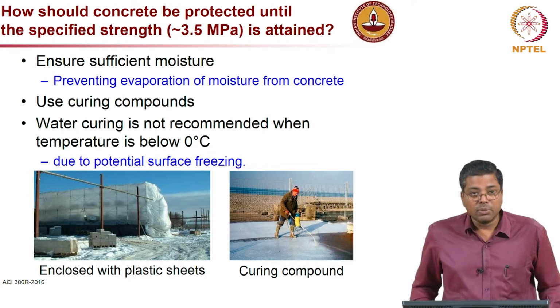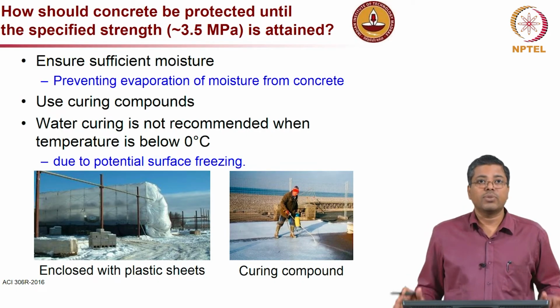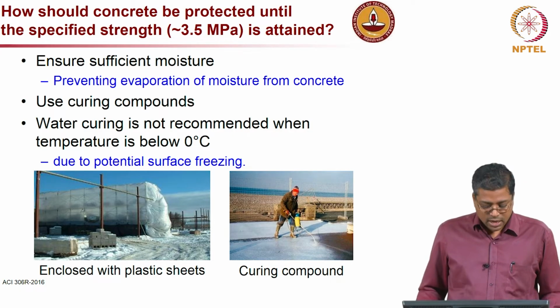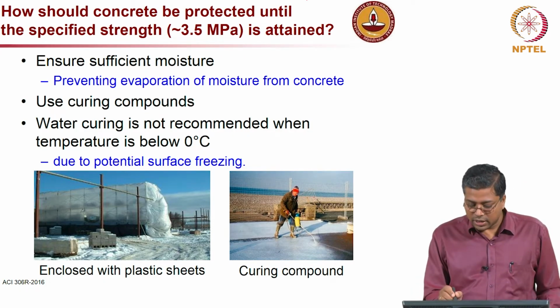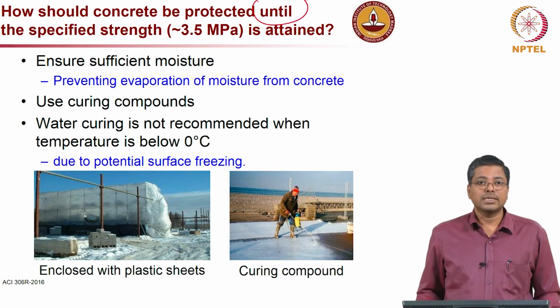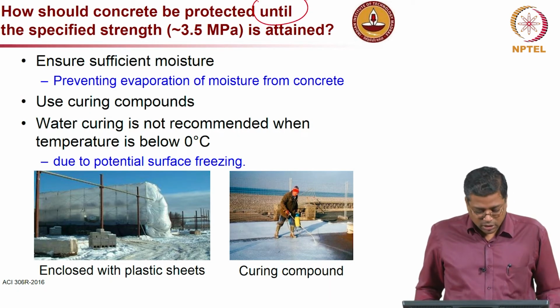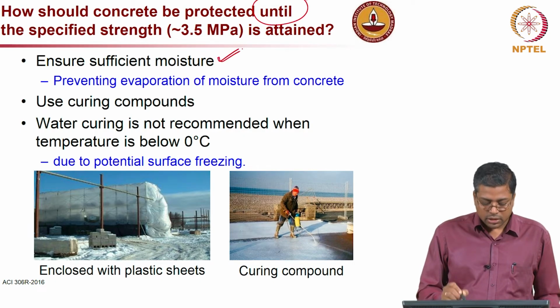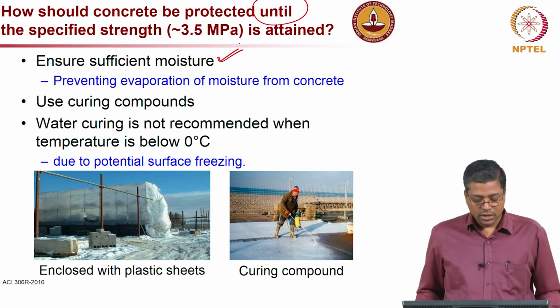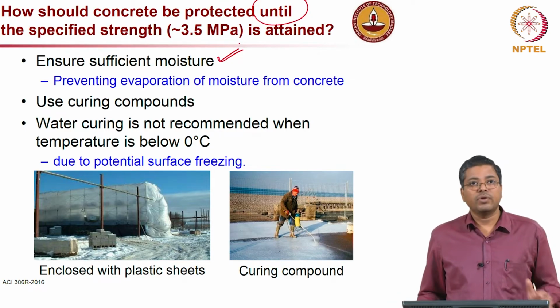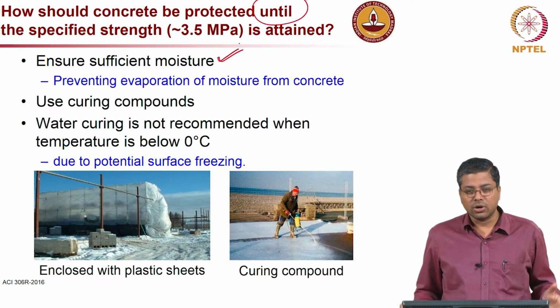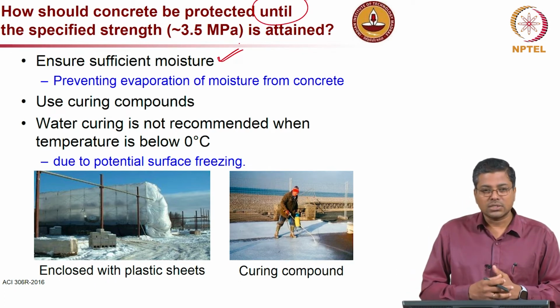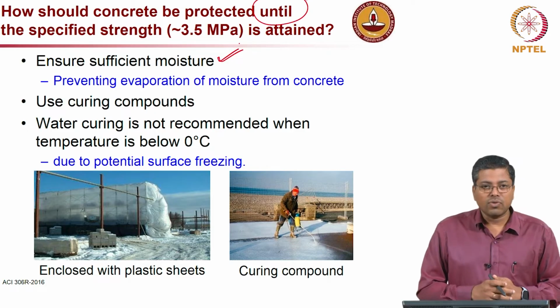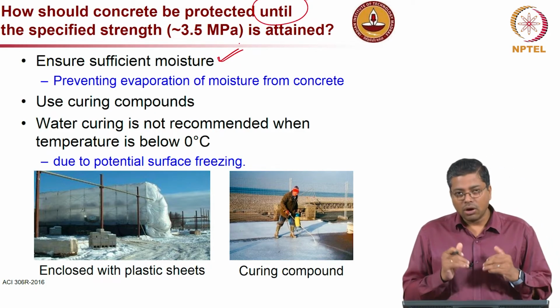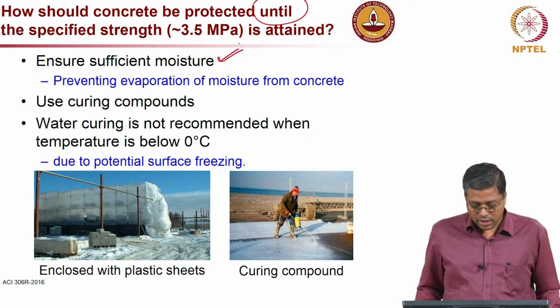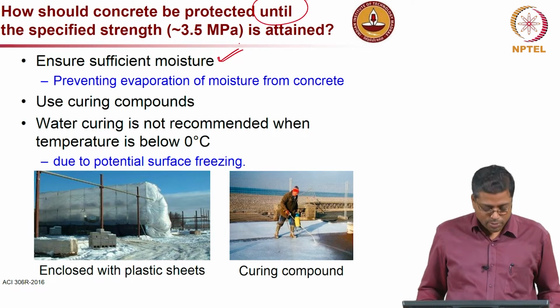Now, how should concrete be protected until the specified strength of 3.5 MPa is attained? Until, the word here is until the 3.5 MPa is attained, that means very early stages in the concreting. First thing is we have to ensure that sufficient moisture is available, and how do we ensure? By preventing evaporation of moisture from concrete, because when you mix concrete based on your water cement ratio, you already have the amount of water which is required for the hydration. All we need to do is prevent it from getting out of concrete, that is, prevent evaporation.